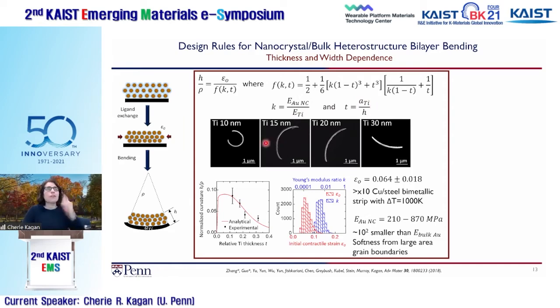So what we did is that, if you see here, as we made thinner and thinner layers on top of titanium, the structures would curl more and more. And what it gave us a way to do, we could measure lots of these structures and start to build up statistics. And they gave us two very interesting measures. One is that we could measure the strain, how much misfit strain was being created once these particles wanted to come together through this sort of compressive force. And so the strain is about 6.4% in our measurement.